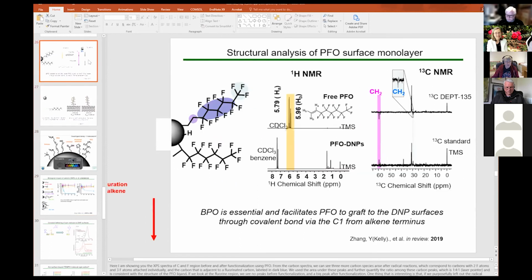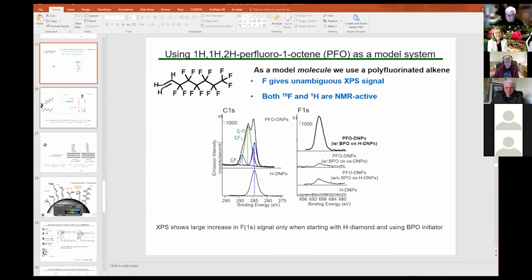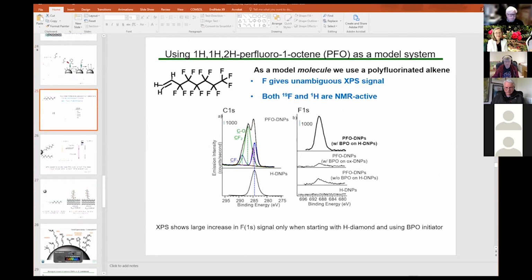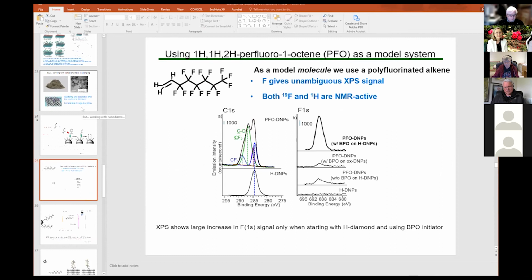Yeah, a key challenge has been you really have to experiment to find the right conditions for this grafting. There might actually be better radical initiators other than benzoyl peroxide too. BPO is kind of a mild one, which is nice because you don't have to worry about polymerization. But it's really a question of getting good miscibility with the solvent so that the BPO and your molecule are both miscible, making sure your solvent doesn't have any reactivity. We've had good luck with dichloromethane, benzene, and toluene, the three that we've had the best luck with. And then it's experimenting. We haven't done enough maybe to understand quite the rational basis for all those choices.